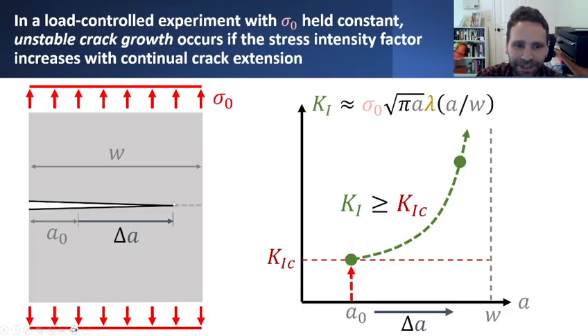And it might not grow this big to begin with. If it started out here, maybe a little bit of crack growth might put it here. So it's like A naught plus a little tiny extra fraction delta A naught. So the crack has grown just a little bit due to the fact that we're satisfying our fracture criterion, and we expect that the crack is going to grow. It's going to extend.